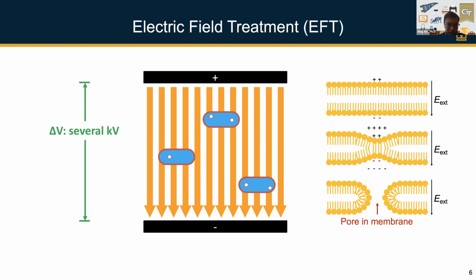So think about that. In our case, if we want to use it for water disinfection or food disinfection, to inactivate microorganisms, you need to achieve even higher electric field strength. That means you need to either apply higher voltage or reduce the distance between the electrodes. As I mentioned, the distance they typically use is already on a millimeter scale, and there's not much room to reduce it further, and that would really limit the throughput of the system. So there's also a big challenge in further increasing the voltage, because several kilovolts is already very high, with very high energy consumption, especially for large scale application. Also, it's not safe for large scale water treatment.